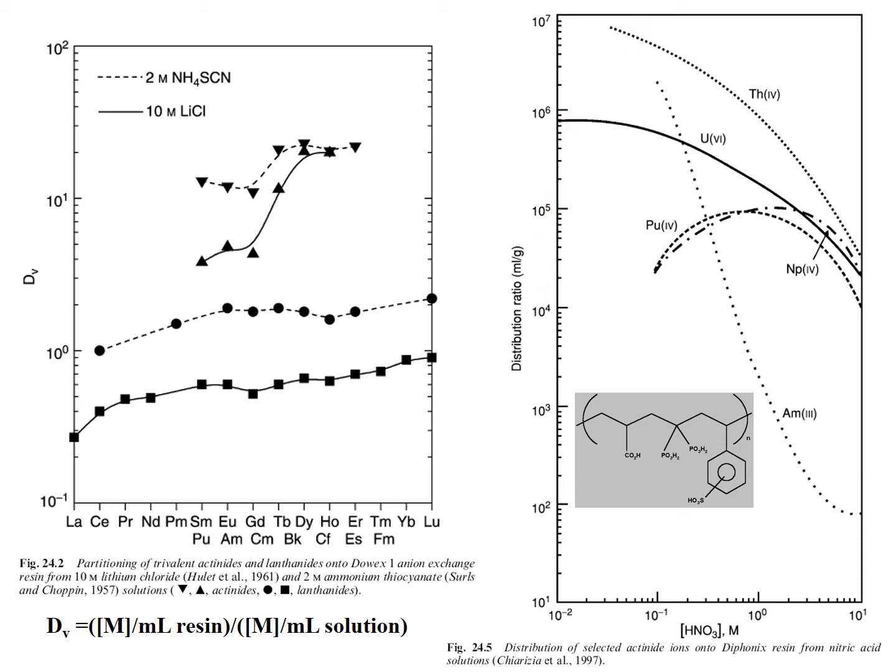And we see as the nitric acid concentration increases, the distribution of the metal ions tends to decrease, the thorium, uranium, americium rapidly decreasing. The tetravalents increase, reach a maximum, and then begin decreasing. And then the lowest distribution is for the trivalents at the higher nitric acid concentration.